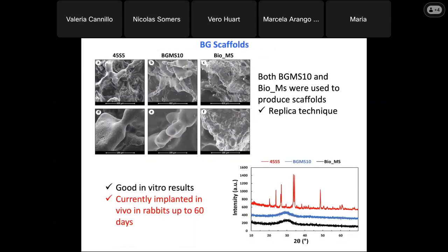So, with these two novel glasses, we produced scaffolds. These are scaffolds produced by a very simple technique, the replica technique, and we produced them using 45S5, but also the two novel bioactive glasses. We obtained good in vitro results. For biological tests, I will not show you everything because otherwise it's too long, but trust me, the results were good. And currently such scaffolds are implanted in vivo in rabbits up to 60 days. We are waiting for these results in the next few days, so I'm afraid I cannot present the in vivo results, but I will be able to do that soon.